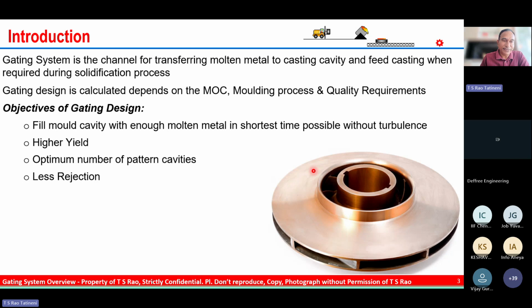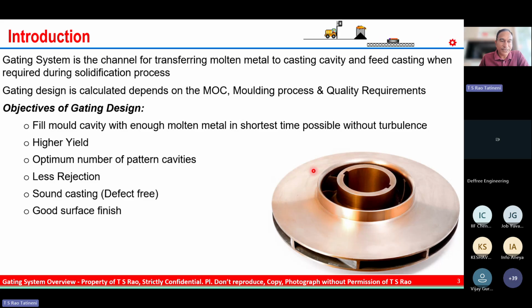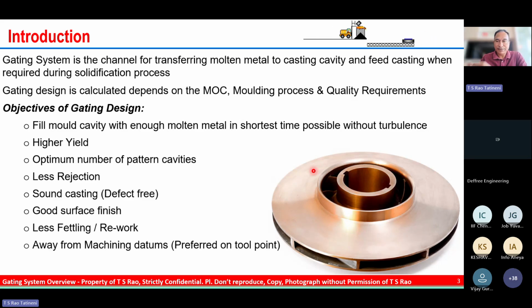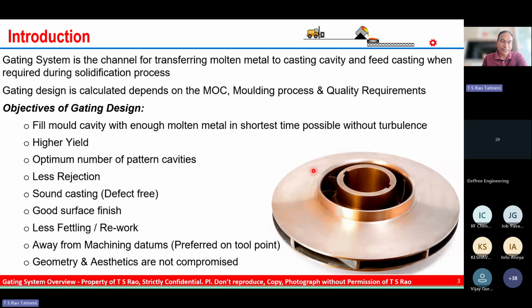And we need to ensure that the gating system gives less rejection, and always we need to produce defect-free casting. And we need to ensure a good surface finish of the product and less fettling or less rework of the product. And the gates should be away from the machining datums. If any gate, because of over grinding or less grinding, the machine datums are likely to get affected. Always it is recommended to have the gating system on the tool point so that it gets removed while machining. So, geometry and aesthetics are not compromised because of the gating system.